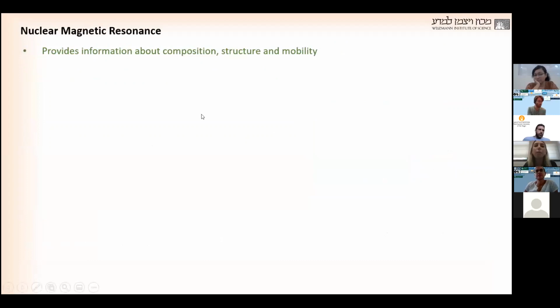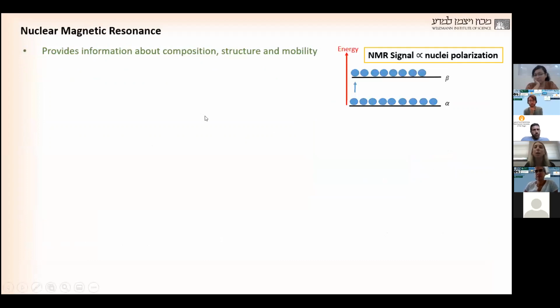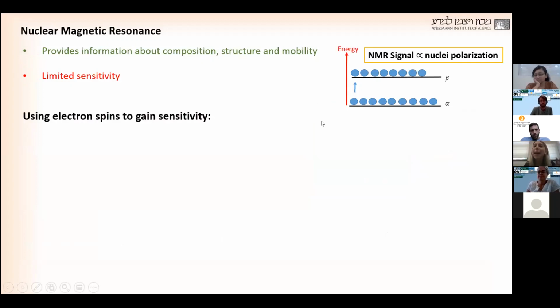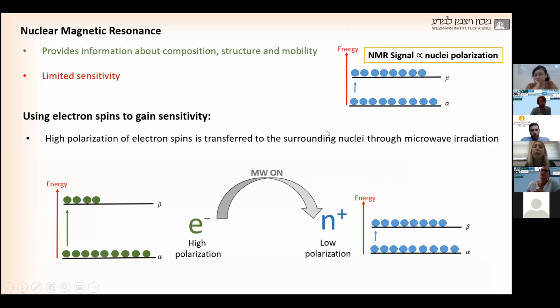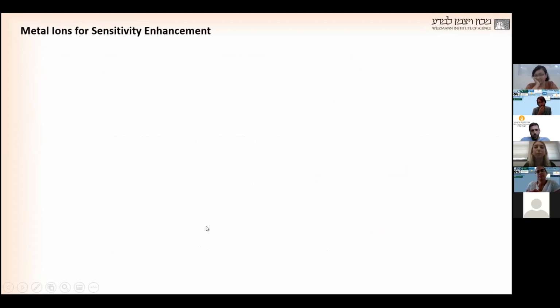NMR provides information about the composition, the chemical nature and the mobility. We can see here that the NMR signal intensity is proportional to the difference in population of the nuclear spins, also called nuclear polarization. But NMR is limited in sensitivity because the polarization of the nuclei is low. So we use electron spins to gain this sensitivity. Electrons have high polarization, as we can see here. And by irradiation with microwaves, we can transfer the polarization from the electrons to the nuclei.